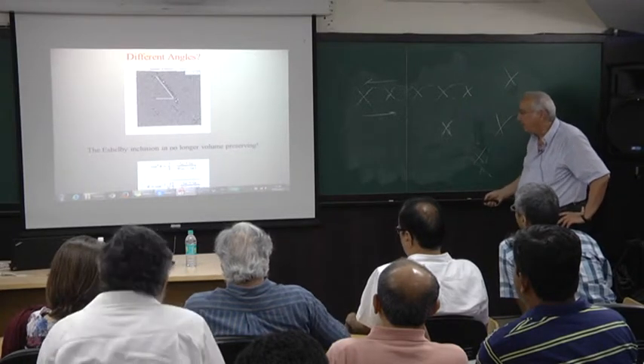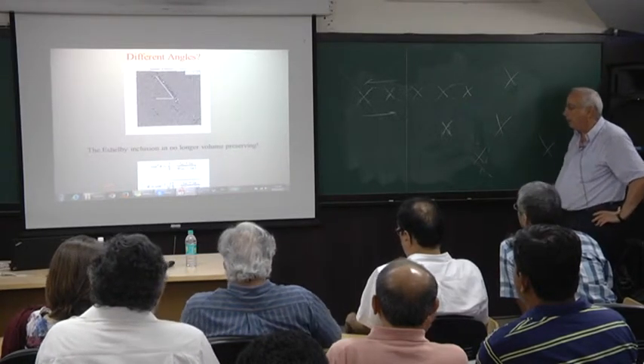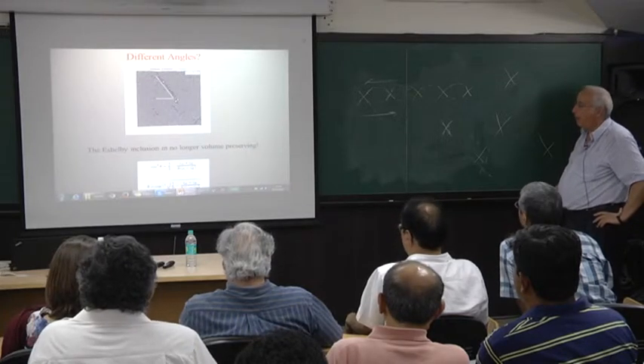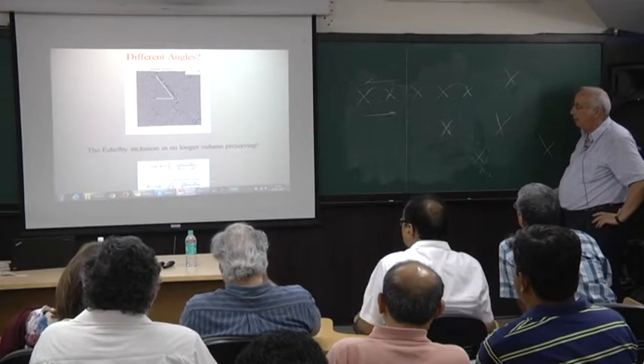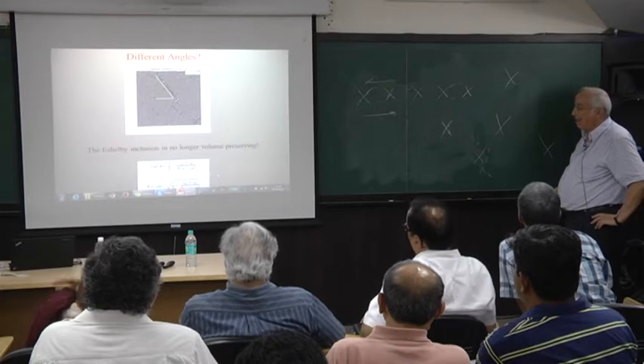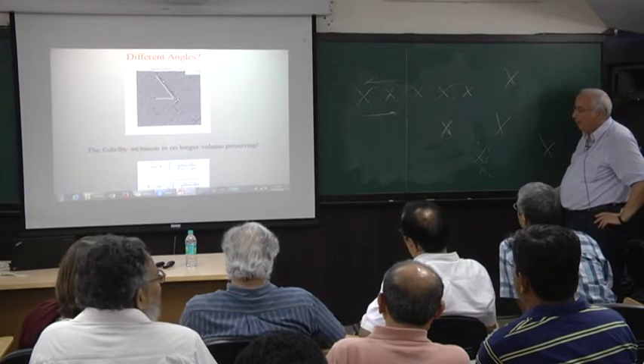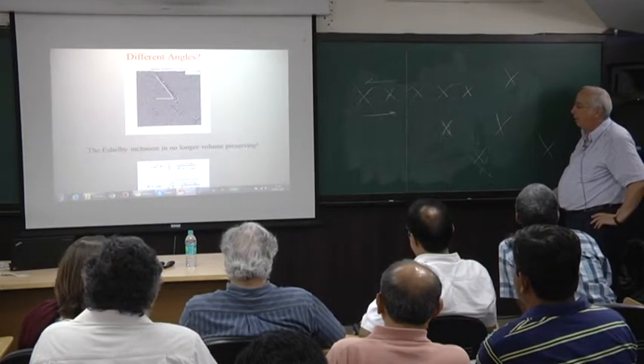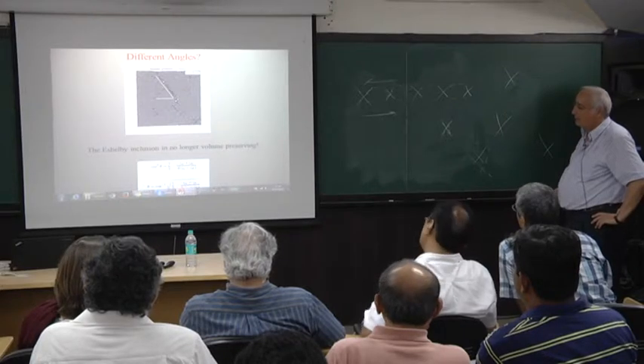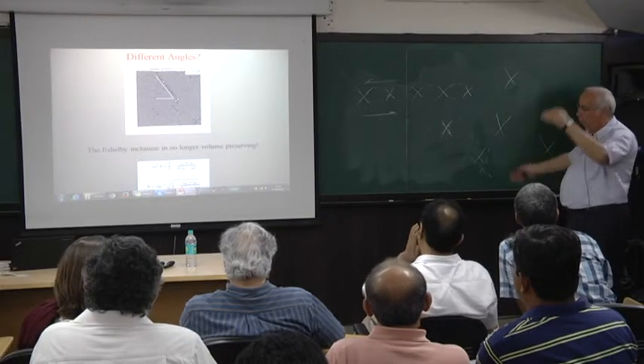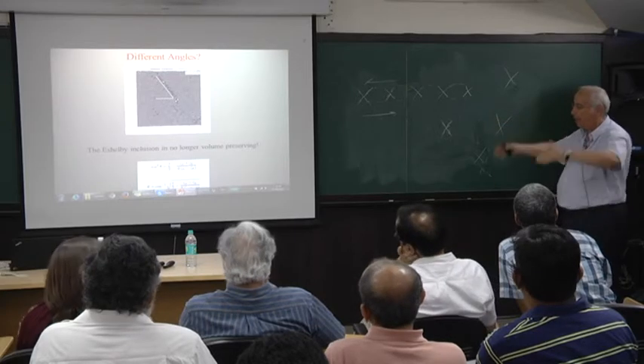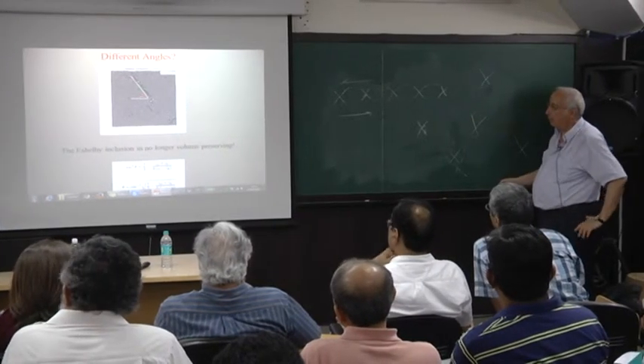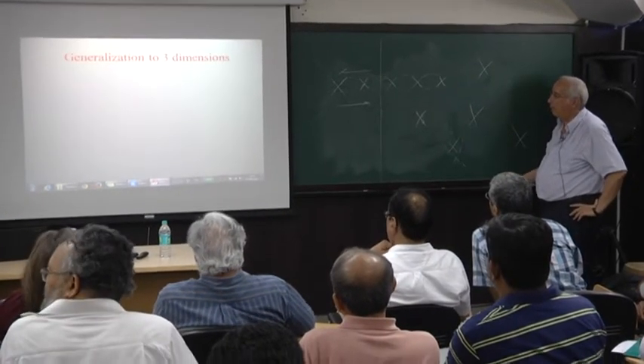I'm sorry that it's down there. But now when you look at the angle, you find the angle, you realize that this angle can be limited between zeta n much larger than zeta k, or zeta k much larger than zeta n, where the two limits are 30 degrees and 60 degrees, and this really depends on where you are, and this agrees very well.